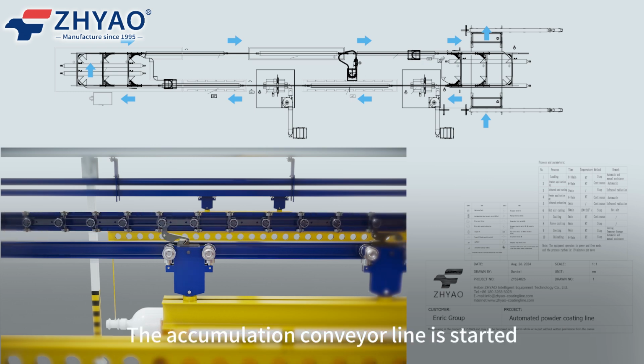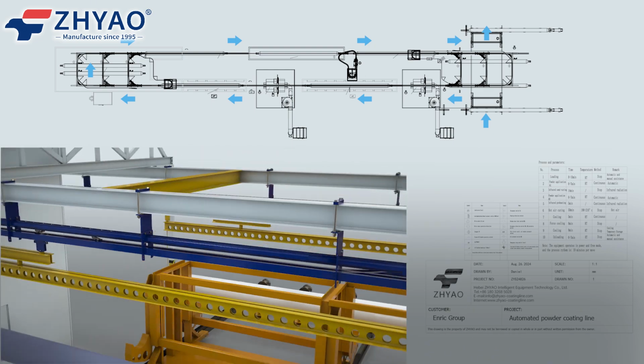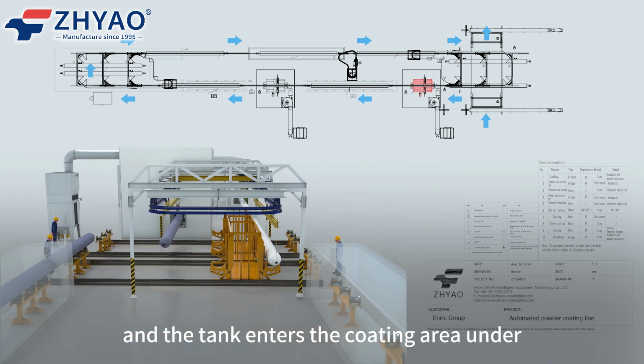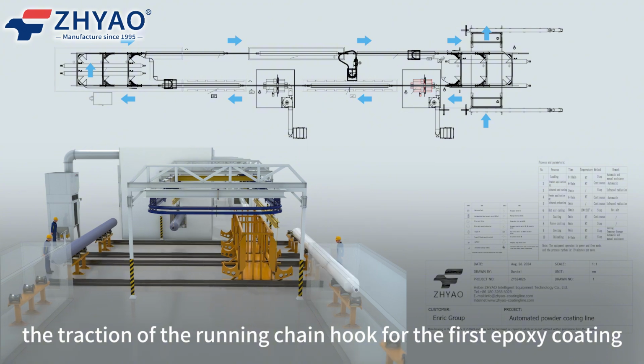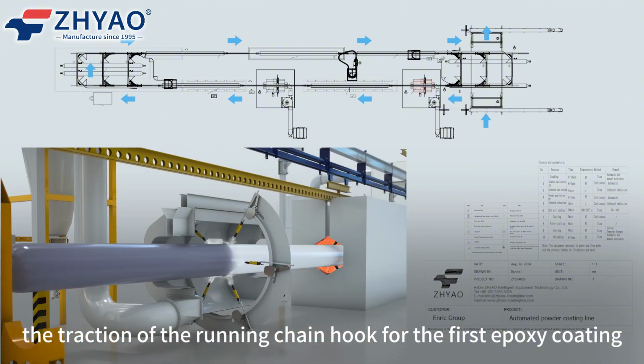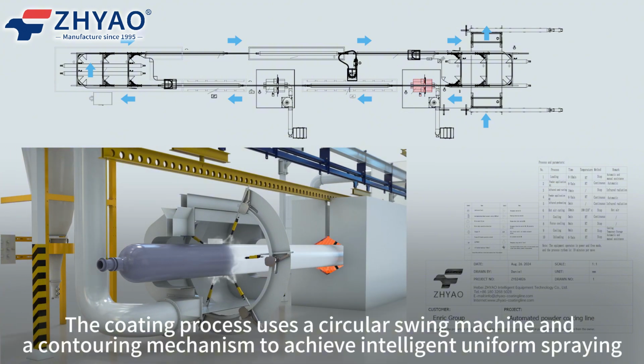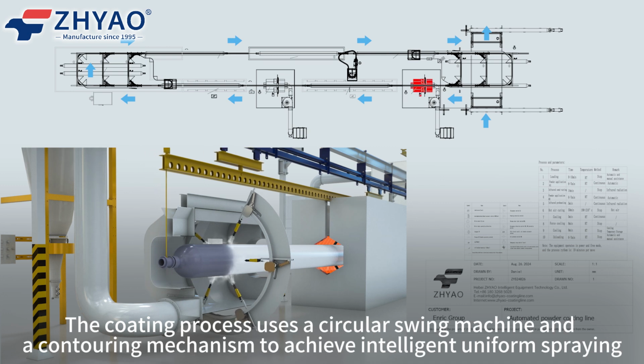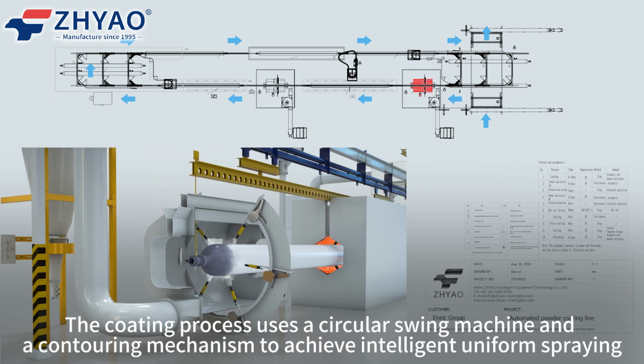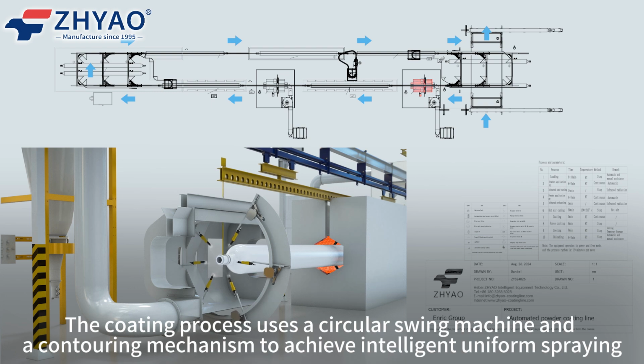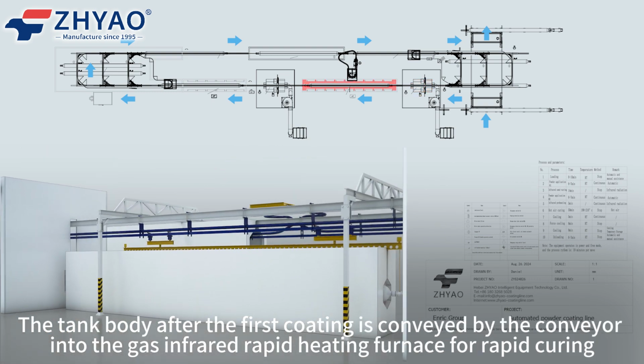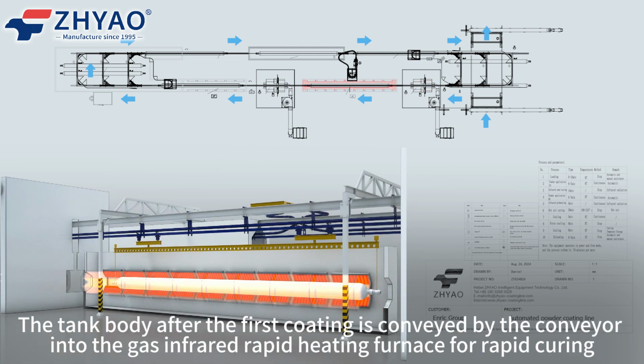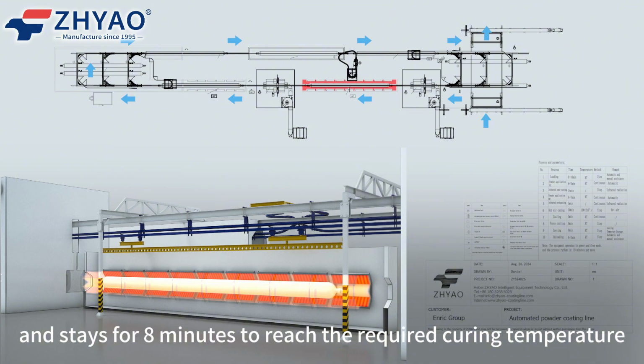The accumulation conveyor line is started, and the tank enters the coating area, drawn by the running chain hook for the first epoxy coating. The coating process uses a circular swing machine and a contouring mechanism to achieve intelligent, uniform spraying. The tank body after the first coating is conveyed into the gas infrared rapid heating furnace for rapid curing and stays for 8 minutes to reach the required curing temperature.